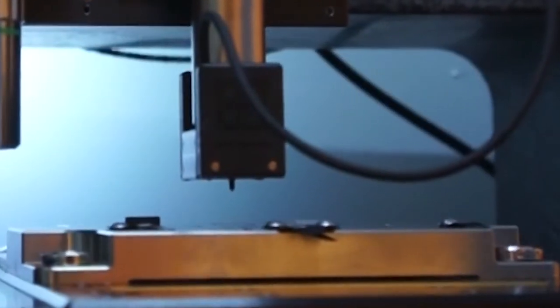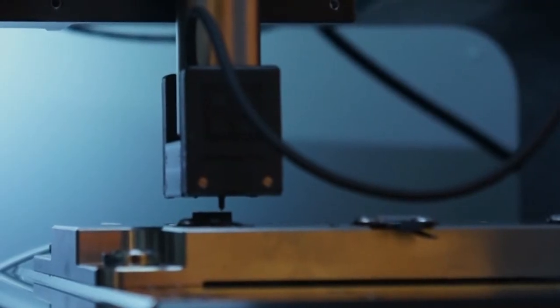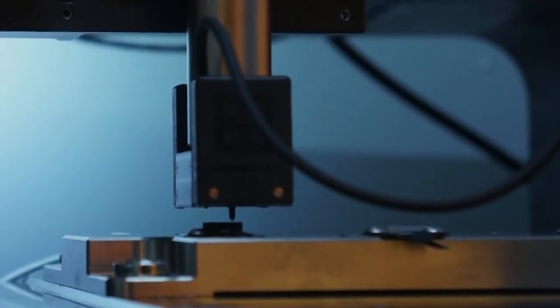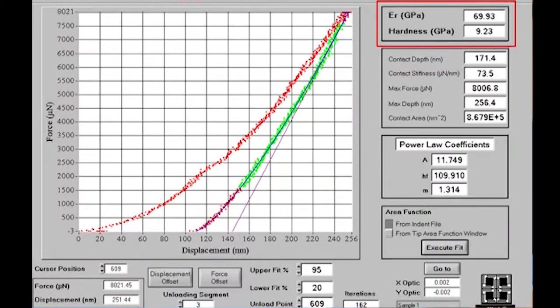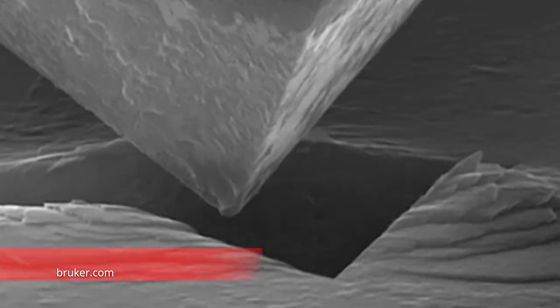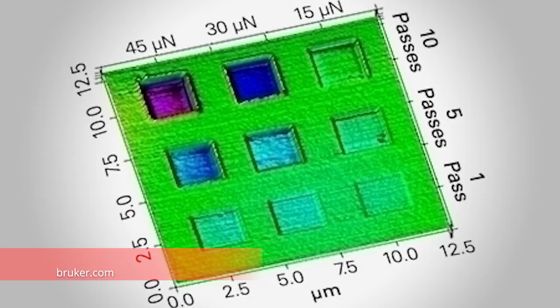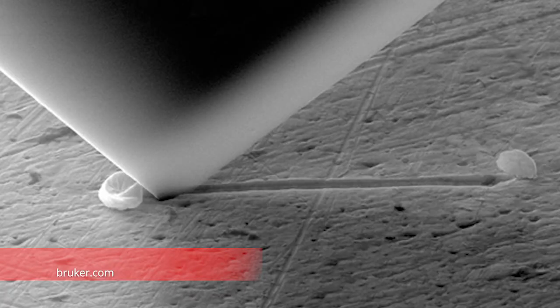It's a great instrument when you need to determine physical properties of a material when the actual volume of the material is very low, like in the case of thin films, or where your sample is too small for other physical testing modes like microhardness or tensile testing. This instrument is officially considered a tribo-indenter because in addition to the one-dimensional quasi-static nanoindentation, it's also possible to do other tribological analyses, including nanowear and nanoscratch testing, where you can test coefficient of friction and induce film delamination, among many other modes.